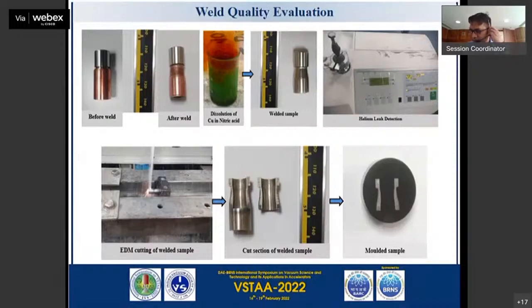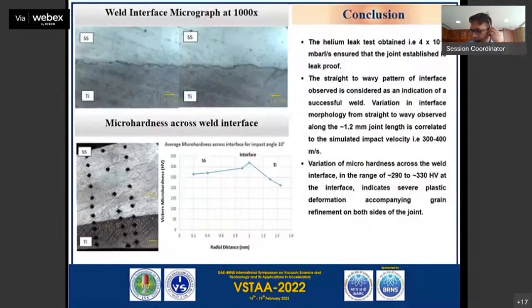Yes, sir. Vacuum comes in the very first weld qualification, which is the helium leak test of the samples. That is the very first evaluation of weld quality that we do for MPW. And what we have achieved is, with MPW techniques, whatever joints we have made, we have got a helium leak rate better than 10 to the minus 12 millibar liter per second, sir. Just another small question. This reprocessing work has been going on in DAE for quite some time, so they must be using vessels where titanium is welded to stainless steel by other methods. What is the advantage of your method? Sir, titanium dissolver units are coming in the FRFCF, IGCAR, which will be doing fast reactor fuel processing, sir.